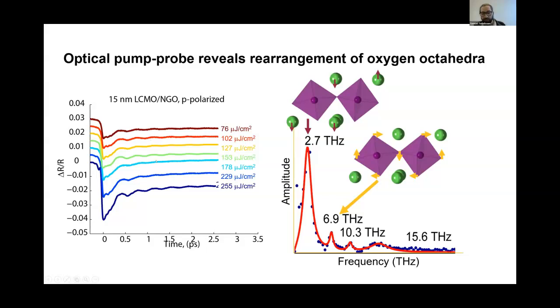And if you do your background subtraction and your Fourier transform, you'll see that there are actually 4 distinct modes in this spectrum. And what these 4 modes are, this 2.7 terahertz mode is what's known as a cation mode. We'll get back to it later. It's essentially the lanthanum and calcium ions moving around to accommodate the oxygen octahedral rotations. And these 6.9 and 10.3 terahertz modes, these are octahedral rotations. So these are the modes that are taking your manganese oxygen bond angle and changing it.